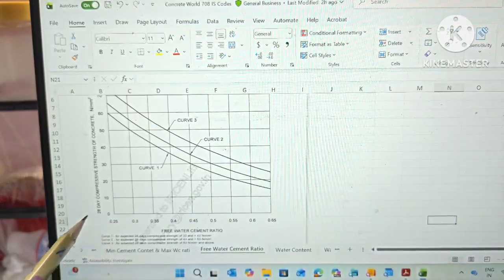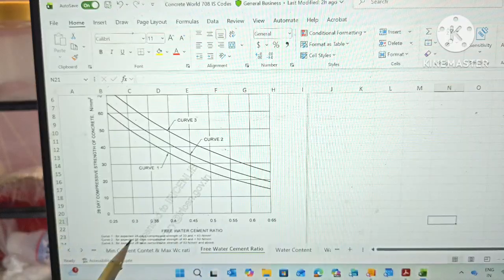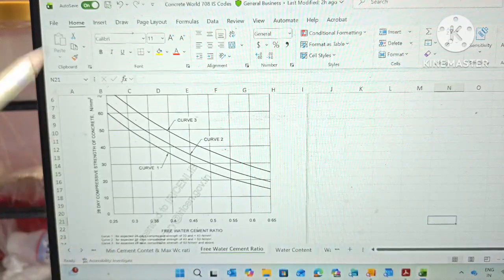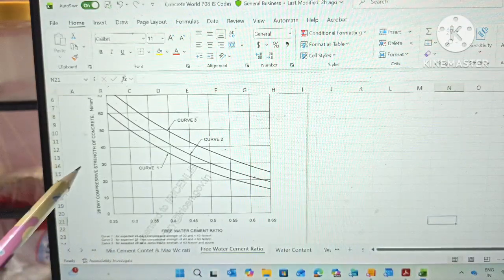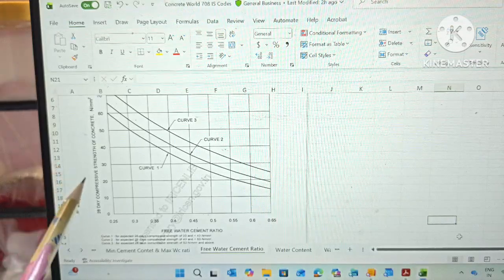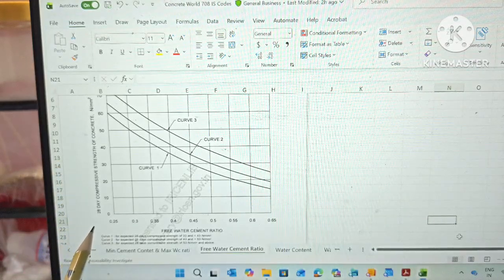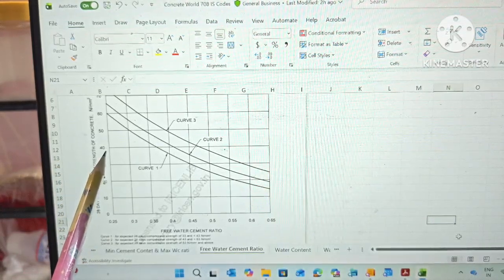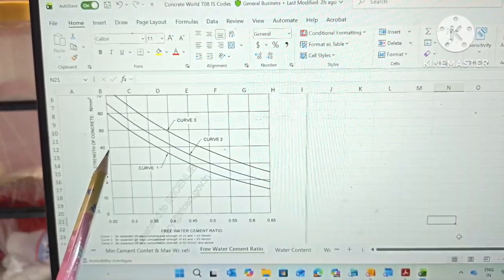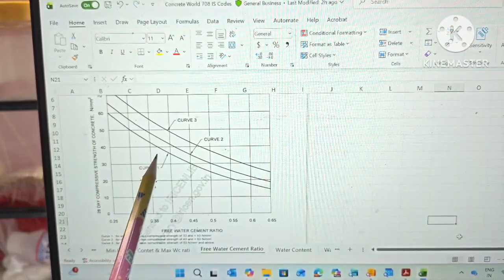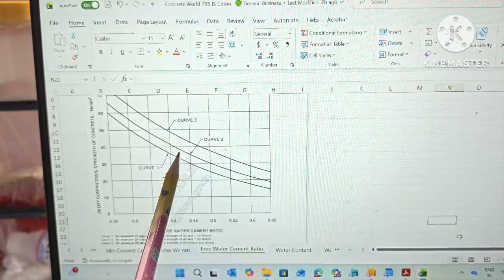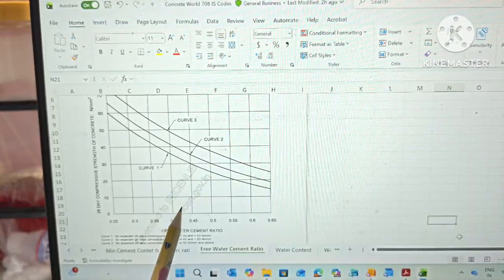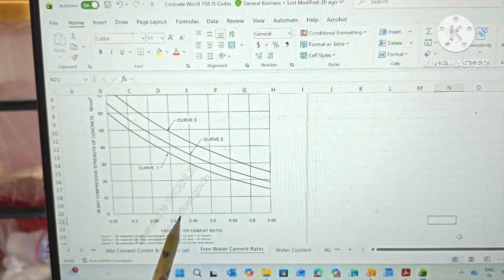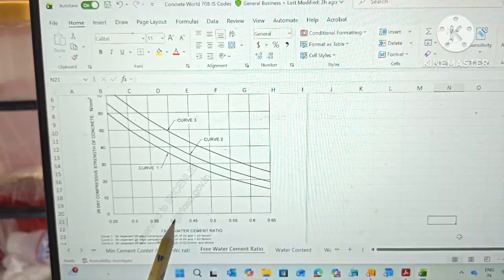In this figure you can see that the x-axis has the free water cement ratio and the y-axis has the 28 days compressive strength of concrete. Now we have achieved a target mean strength of 38.25, which comes around here. If we go in a straight line and intersect curve 2 and go down to the water cement ratio, our water cement ratio comes between 0.4 and 0.45, so we can consider this as 0.42.